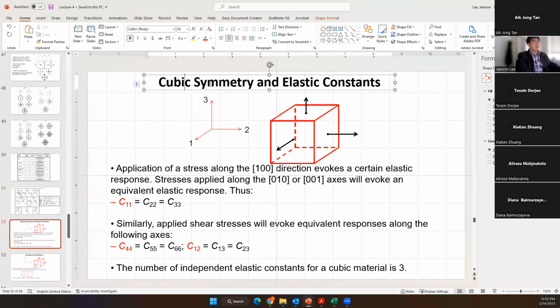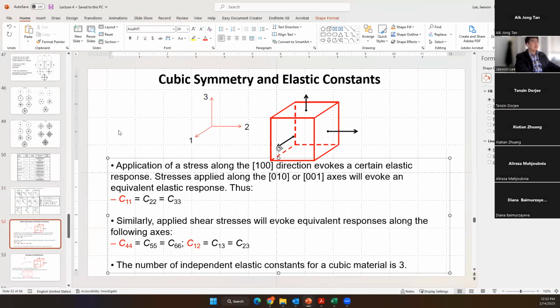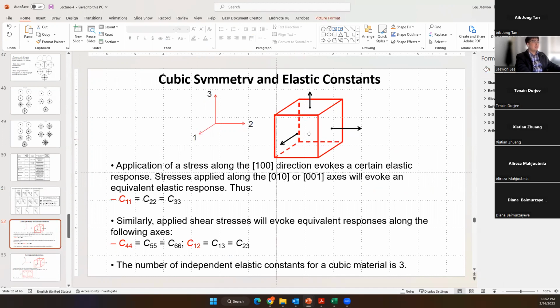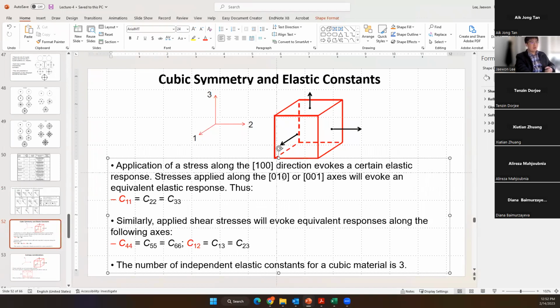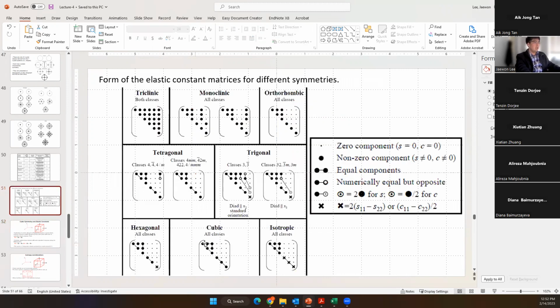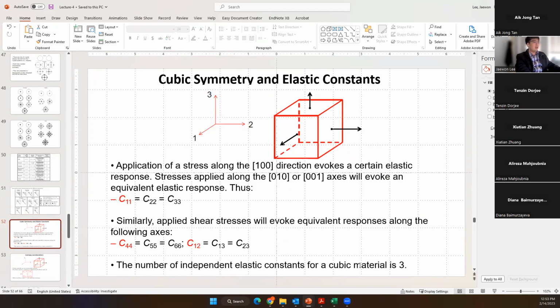So this is the cubic system, cubic symmetry and elastic constants. If we focus on the stress in the 1, 0, 0 direction, it is related to the 0, 1, 0 or 0, 0, 1 axis. So we can make C11 equal to C22 and C33. And then shear stress is also equivalent around this axis, so C44 equals C55 and C66. And C12 equals C13 and C23. So the independent elastic constants for cubic material is only 3.